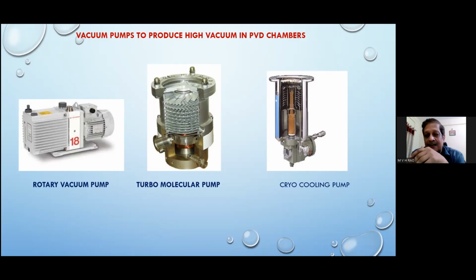This is particularly required for water vapor. If water vapor is the main issue, then a cryo pump has to be used because it very efficiently pumps the water. For this reason, normally in any vacuum chamber, the pumping is first done with a roots rotary pump to get a 10^-3 vacuum. Only then we switch over to high vacuum, so from 10^-3 to 10^-6 we use turbo pumps, cryo pumps and many other varieties.